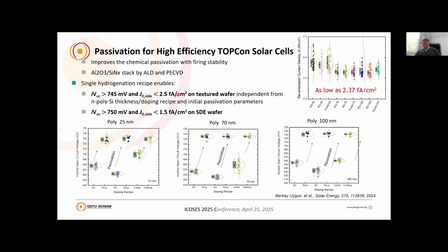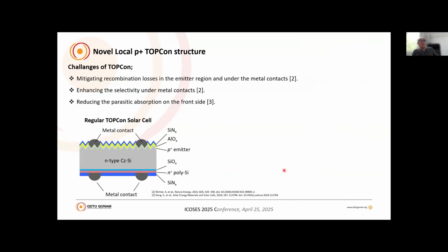The recombination current density on the backside will be as low as 1.5 femtoampere per centimeter squared. So these values are really very promising. But of course, reducing the polysilicon thickness is an important issue to reduce the parasitic absorption on the backside. This is also something that we are studying, and you can look at this paper if you would like to know more about this.